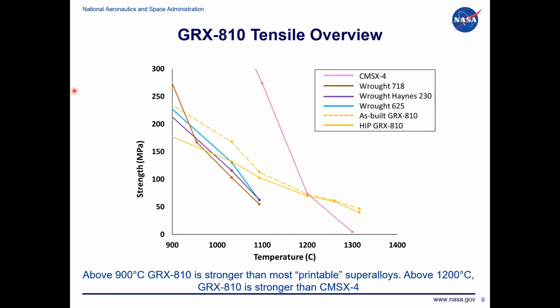But what's interesting is that you never really hit that cliff that a lot of other superalloys have before they melt, where they lose all their strength. And in fact, by the time you hit 1200 C, you're starting to get tensile properties that are closer in line with what you might get with a single crystal. Again, single crystals aren't usually used at those high temperatures without cooling, but it shows how incorporating these nanoscale oxides can really push the possible operating temperatures for these alloy systems.